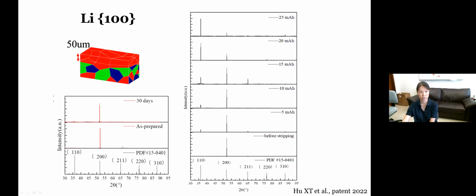Right, this is the as-prepared sample. You see a preferential X-ray diffraction from the 200 planes, telling you we obtained the texturing of the 100. And this structure is quite stable. Here's the data. When the sample is stored in the glove box for 30 days, it actually can be longer. It stays for a month. Until now, it's still very stable.